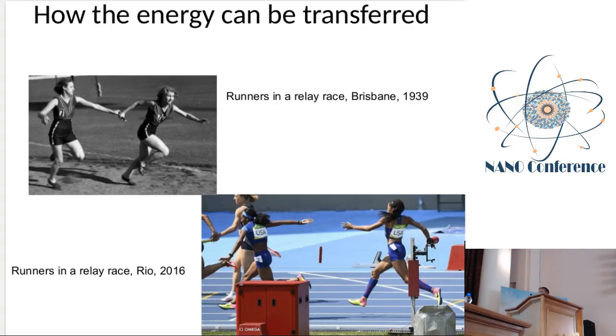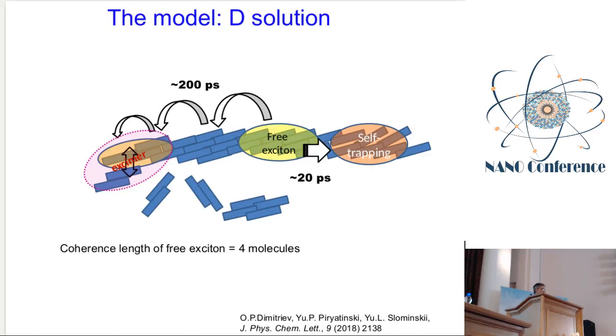So coming back to our results, we can describe the mechanism of energy transfer by the delayed process. The delayed process is due to the diffusion of the exciton to the specific sites, where the energy can be transferred to the other species. For example, if we have a pure donor solution, we have energy transfer to dimers, and we have an excimer excitation here. But if we have a mixed solution, there is a competition between excimer and exciplex formation, where the foreign species can interact with the sites and give exciplex formation.